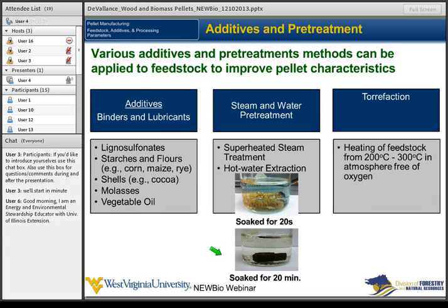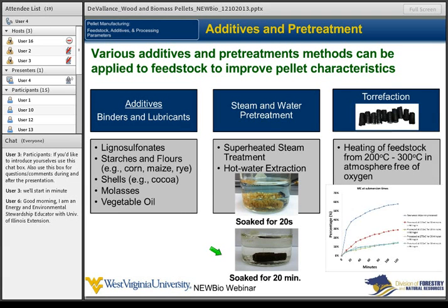So you can do things in terms of removing, in this case, hemicellulose to improve its durability. The next thing is torrefaction. This is gaining popularity and it's heating of feedstock. These temperatures vary, but 200 degrees Celsius to 300 degrees Celsius in an atmosphere free of oxygen. So you can see some torrefied pellets up on top. They turn black, have a high carbon content, properties closer to what you would find in coal, and they're said to be hydrophobic. Okay, they tend to not take up water as much.